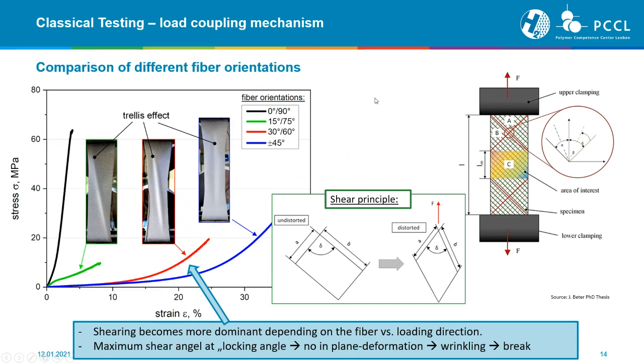However, focusing on the woven fabric, we've implemented tests here, first of all, with setups where we only have 1 and 2 layered systems, where we characterized some different fiber orientations. For example, here you see the fiber orientation 0-90 degrees, where we received a very stiff material performance compared to ±45 degrees, where we have a much higher strain, or a much larger strain, compared to the lower stress when we compare it to the 0-90 degrees.